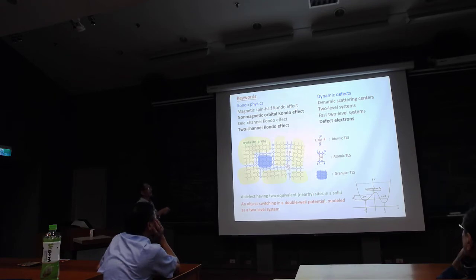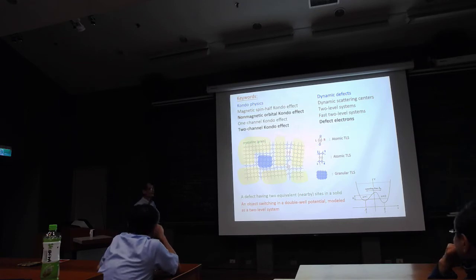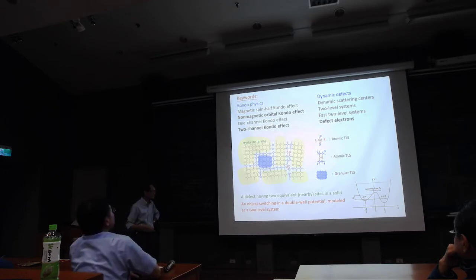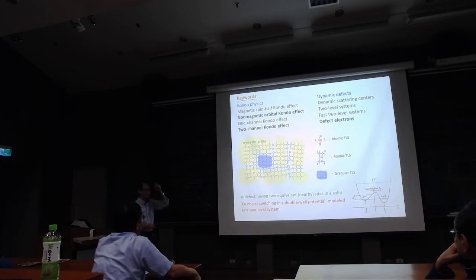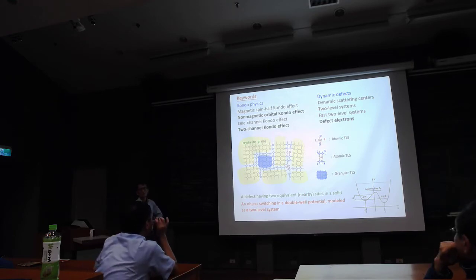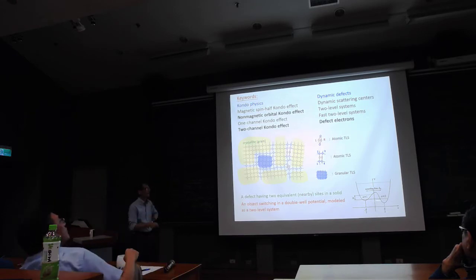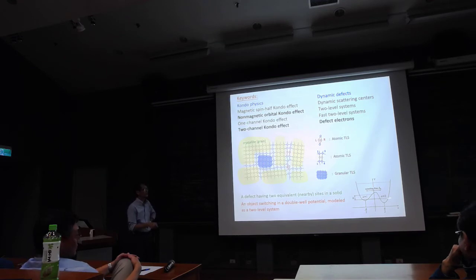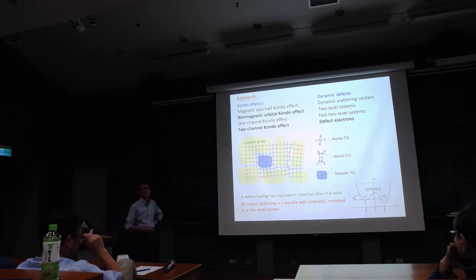So the basic idea about a dynamic defect or scattering center is that you have an object moving back and forth. And in old days, many people believed that the object moving back and forth is an atom, for example, an oxygen vacancy. And nowadays, today we have a different story, and the moving object actually is an electron, because atoms are too heavy to give you a very fast fluctuating rate, or to give you a big enough energy scale. So we have dynamic scattering defects. This has two sides, and if conducting electrons couple with this defect with an internal degree of freedom, then it can cause the Kondo effect.